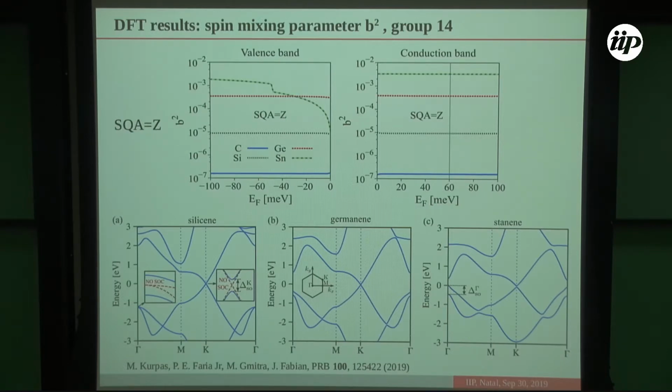But what is important here is that you see that if we change doping, those values don't change. The reason for that is that we start our Fermi level here. So if we lower the Fermi energy, we go here on this cone, but this does not change because there is no other bands that could contribute to the spin orbit coupling here, because all of those bands lie really low in energy. So we can say that spin orbit coupling here is constant in this band.